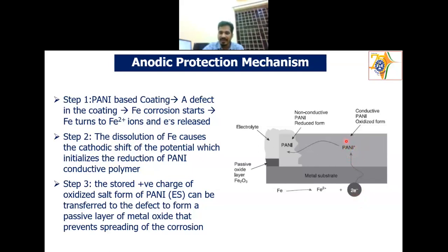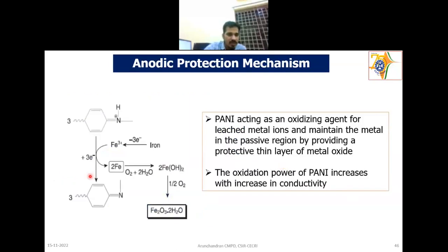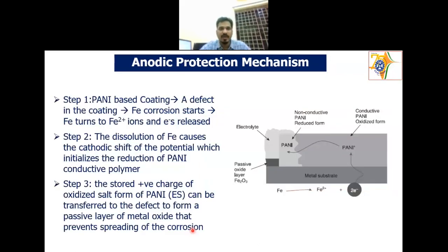When we move here, it gets reduced and becomes Pani EB form. The stored positive charge of the oxidized salt of Pani, ES, can be transferred to the defect to form a passive layer, an oxide layer will form. So it's kind of an ennobling mechanism. You can see here when the iron becomes Fe3+, the electron is coming, the electrons were used by the Pani, and in the presence of oxygen and water, an Fe2O3 film is finally formed at the defect. This is the anodic protection mechanism for the Pani.